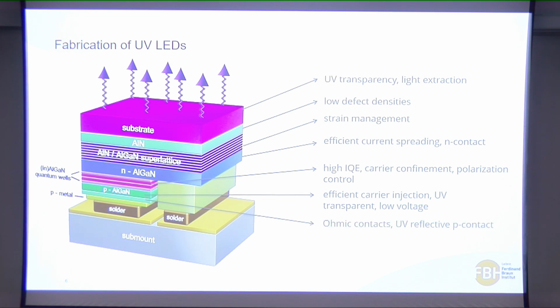And then you have the ohmic contacts, so the P ohmic contact and the N ohmic contact. And once again, you need really good contacts so that you have low voltages of your device, and in the best case, you would also like to have UV reflective P contact so that you can extract the light out of the LED. So I can show you there's really a lot of challenges, and we and other groups are working on each of these layers to try to improve the external quantum efficiency of the LED.